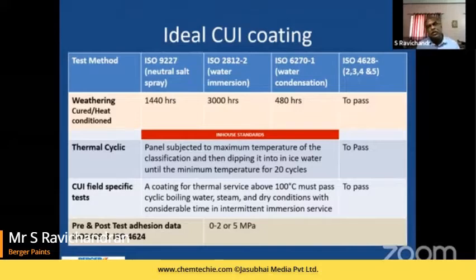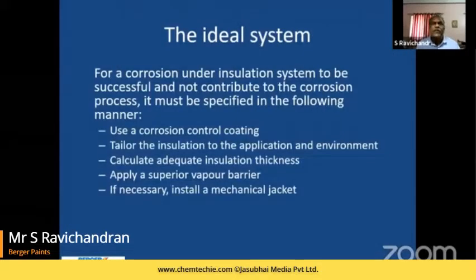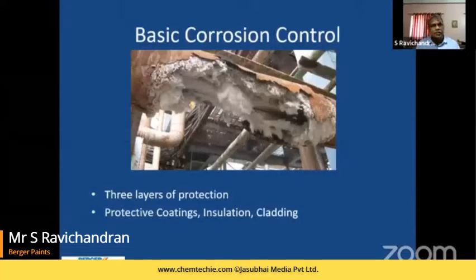The adhesion of any coating is very important, and a range of between 2 to 5 megapascals is considered a very good coating adhesion. And therefore, we'll be in a position to recommend such types of coatings for these services. So when you look at an ideal system for a corrosion under insulation coating, it should not only be successful in handling the corrosion, but also be compatible with the insulation. It should offer you the barrier properties and also be compatible with the service operating conditions. So when we talk about corrosion under insulation, we try to handle 3 layers of protection. The protective coatings have to be in place. The insulation has to be there and perfect. And the cladding has to be there, which is going to protect the insulation.